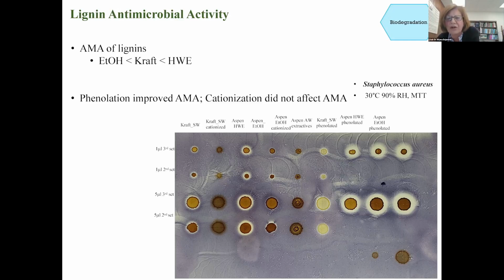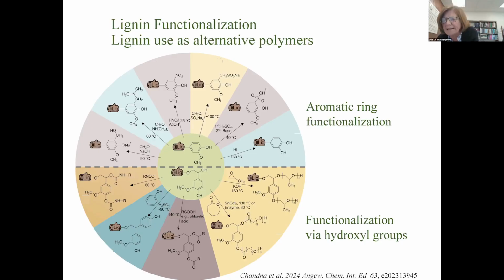Here on Staphylococcus aureus, we see those white halos, which means that microorganism stopped growing, and lignin shows again different antimicrobial activity depending on the type. But in addition to blending lignin with polymers, lignin can be used after functionalization either individually or in combination with other polymers as an alternative to current conventional synthetic polymers.